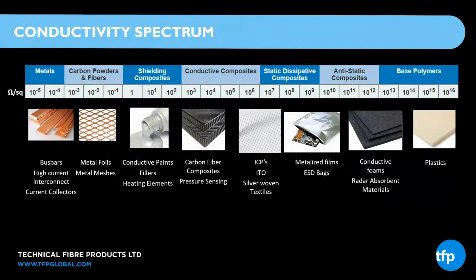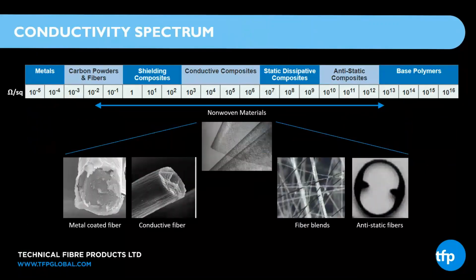So this here is a conductivity spectrum showing various materials. On the left side, you have your very conductive materials like copper bus bars, and on the right, you have plastics, dielectric materials. We like to say that we play in this region. On the left side would be our copper nickel coated carbon veils, and on the right would be our glass veils. Anything in between we can make using a combination of the fibers. So we could combine carbon and glass to change up the conductivity.